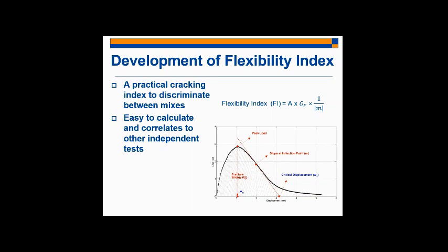And so let's talk about the structure of this index a little bit. Basically, a material that gives me a higher slope of the line fit to the first inflection point past the peak load, the higher that slope, the more brittle my material is, right? And so the higher my slope, the more I can penalize the mixture for behaving in a much more embrittled fashion. The fracture energy we included because the fracture energy still tells us something about the behavior of the material.